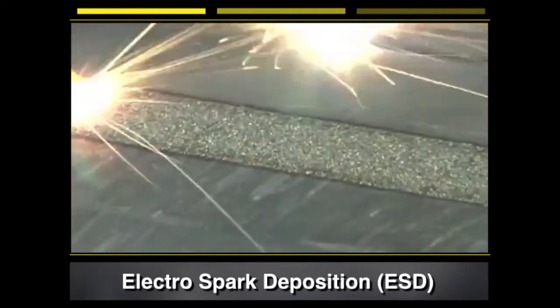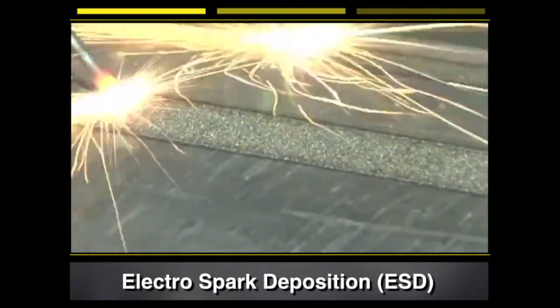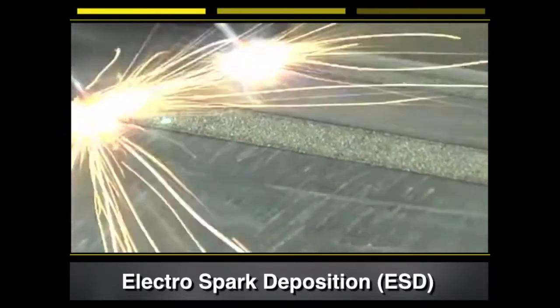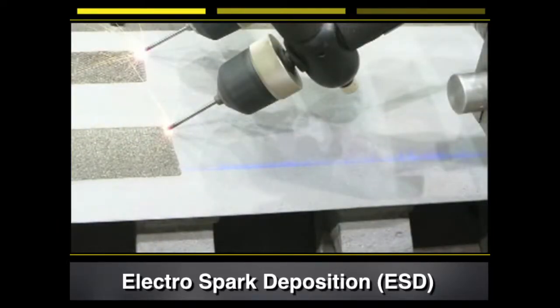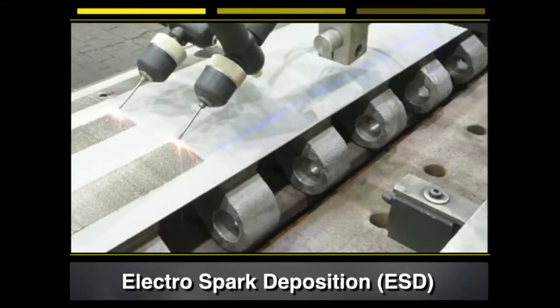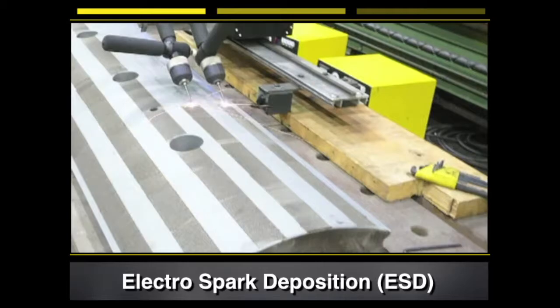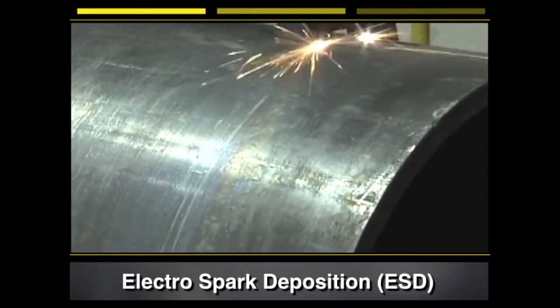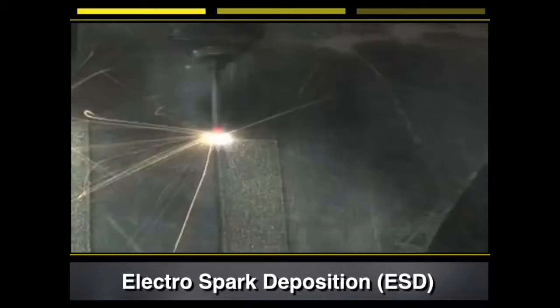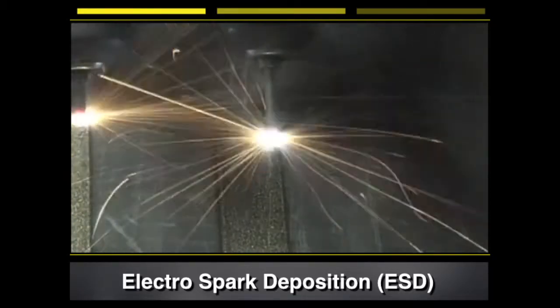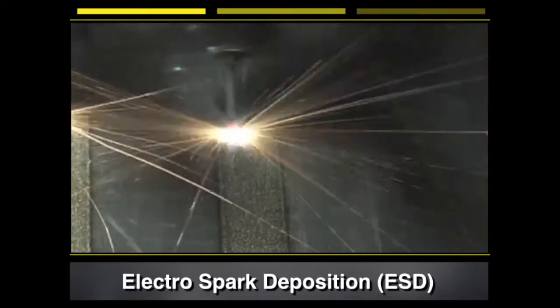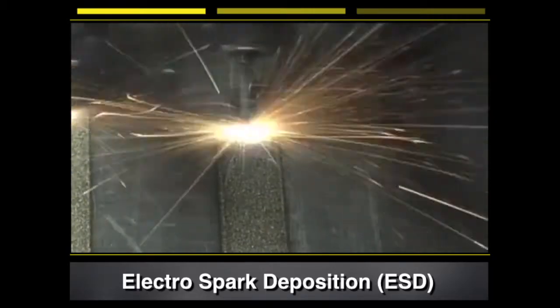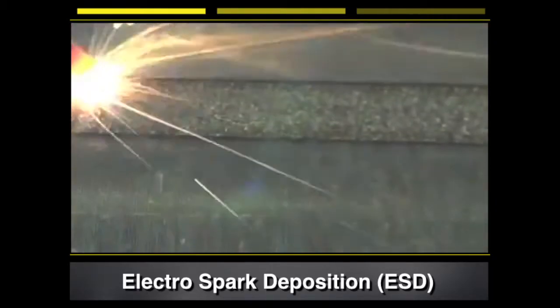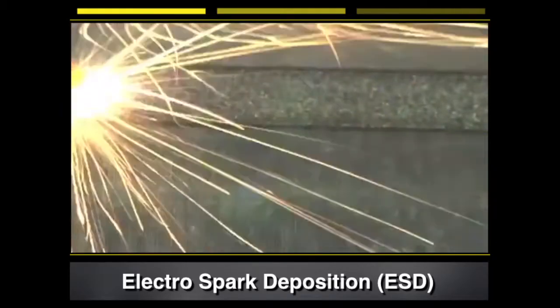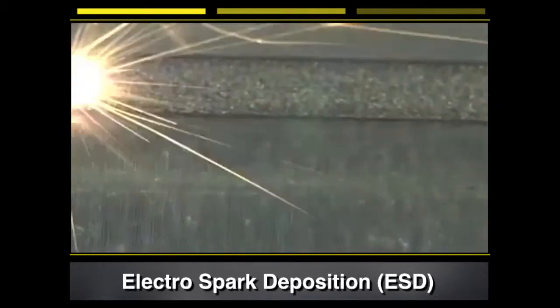The emerging technology in the texture field is actually an older technology commonly called ElectroSpark Deposition, or ESD. Carbinite has sort of hot-rodded this technology within the past couple of decades. We've been able to make technological improvements that have led to an increased rate of deposition and much rougher surfaces when desired. As you can see here, the consumable carbide electrodes are spinning in order to break contact. The arc is relatively short and usually does not need an inert gas shield. This new hot-rodded technology has made larger applications more feasible in terms of cost effectiveness.